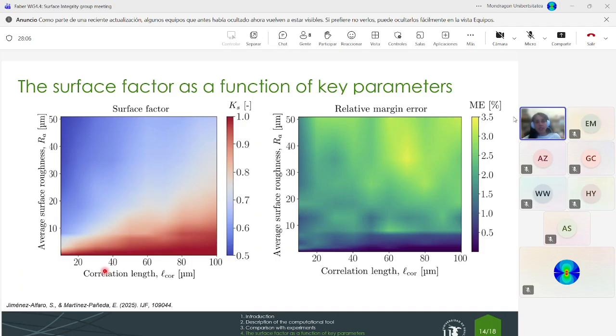So in this case, you can see that when we have a correlation length that is really big and an average surface roughness that is small, then the effect that the roughness has on fatigue is almost negligible. But this can be really critical when we go for values of the average surface roughness that are very big and a correlation length that is small. In that case, we can even arrive at a value of 0.5. Imagine, this means that for 1 million cycles in the polished specimen, we have 500,000 cycles of fatigue life for this rough specimen. So it's really, really critical.